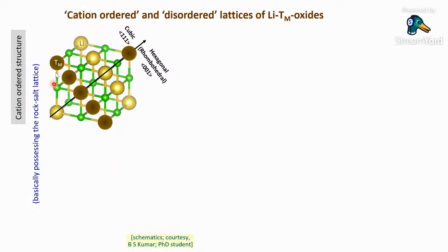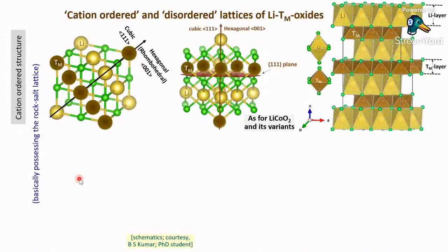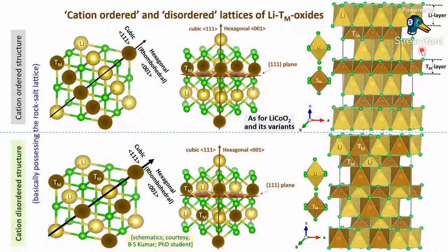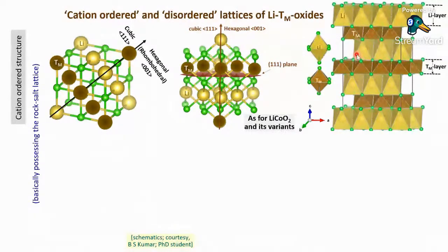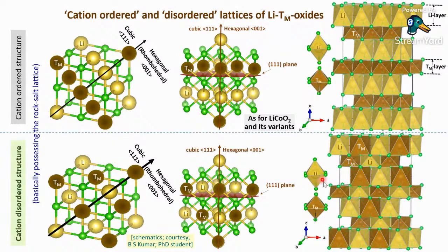Now, in this rock salt type of structure, if the transition metal ions and the lithium ions get separated out into alternate 111 planes, one can visualize this in terms of a layered structure if one rotates the unit cell to make the 111 axis in this direction. So now one can visualize this 111 plane as a transition metal layer, this 111 plane as the lithium layer, and that is what is shown here in a way which is more commonly used to represent these layered transition metal oxides. Now, such nice ordering or layering allows a facile pathway for lithium ions to move out or go in, unlike what would have happened had it been a cation disordered structure where there would have been no specific plane or layer allotted to lithium or transition metal ion. So lithium would face a lot of difficulty moving in and out from such a cation disordered structure.